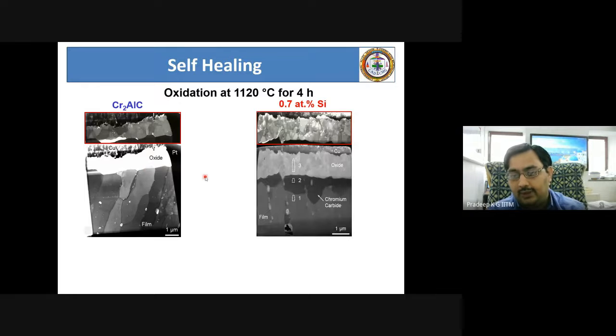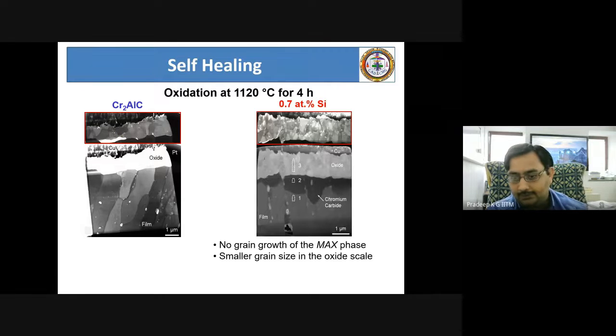which is a protective self-healing coating. Now in the presence of silicon, as we notice, the grains that are formed in the oxide are much finer. This is the same oxide that I have magnified here. You see the contrast here, the grains are much finer in the presence of silicon, whereas in the absence of silicon, the grains are much coarser. That means you get a smaller grain size when you start adding silicon to a MAX phase.